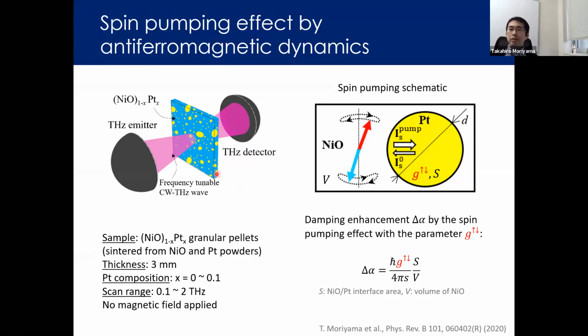So here we examine the spin pumping effect in the nickel oxide platinum structure. The sample used here is a nickel oxide platinum granular system where platinum granules are dispersed in the nickel oxide matrix. This is also made by the sintering process. We start from mixing a platinum powder and the nickel oxide powder, and then press them together and fire it to make a bulk pellet.